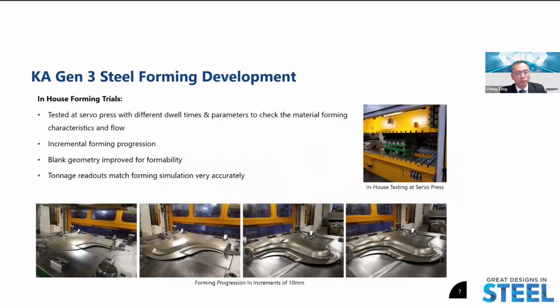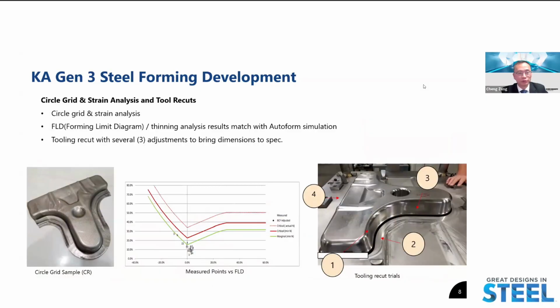Okay, and then in-house we also brought it to the servo press for different parameter trials under different dwell times and parameters to check the forming characteristics as well as the material flow. We incremented by 10 millimeters here, and then we see where the material could go. And you can see here, this is the first, and then 20, 30, and 40. Okay, and this is a significant improvement. You see here, we changed from the original square blank to one with a big radius, which helped with stress concentration mitigation. And then the tonnage readout also matched the forming simulation very well. That built a very good confidence for us to use in future production.